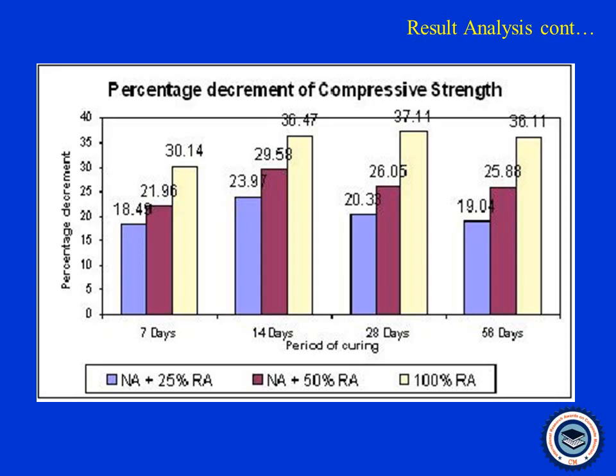From the above results, it was very clear that the recycled aggregate could be used as a structural concrete with some modifications in the mix design. In mix design, for achieving the expected strength, the cement content may be increased and the slump must be checked for the workability. So the adhered mortar over the recycled aggregate also should be cleaned. So the treatment of aggregate also will give you better strength results.